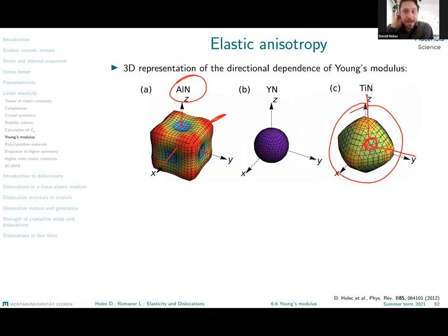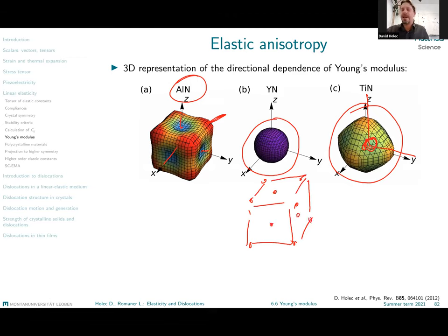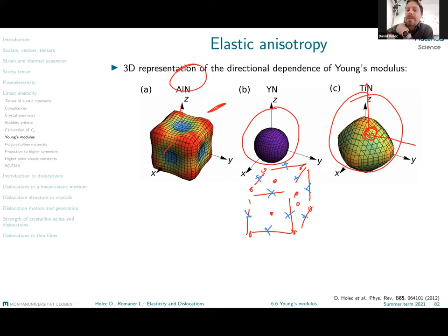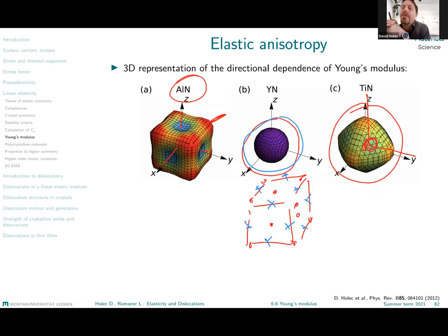If the resulting directional dependence of Young's modulus is directionally independent, that means the visualization yields pretty much a spherical shape, you have an elastically isotropic material. Again, it does not mean that your material is amorphous or that it is structurally isotropic. No, we speak here indeed about the B1 structure, the rock salt structure, where the atoms are very clearly on a cubic FCC-like lattice with the nitrogen atoms sitting in the interstitial sites everywhere here. So this is structurally completely non-isotropic material. It is clearly cubic material, but the elastic response here is elastically isotropic. So no matter in which direction I load it, I always get the same deformation.